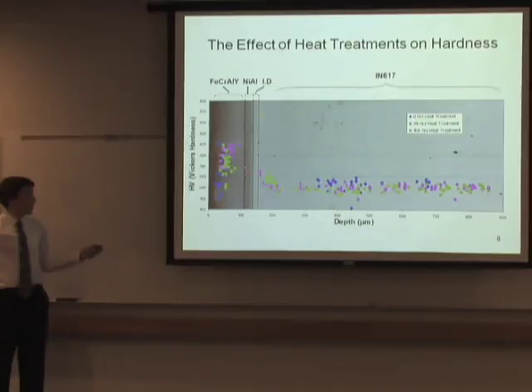And next, the NIAL region, which has no indents simply because it's too small for microindentation. And then in between the NIAL region and the Inconel region is a small layer called the interdiffusion zone, where elements have accumulated due to interdiffusion from the Inconel region and the NIAL region. And you can see that here they have a slightly higher concentration of hardness due to an increased concentration of aluminum. And lastly, the Inconel 617 layer has a Vickers hardness of around 200 to 225.